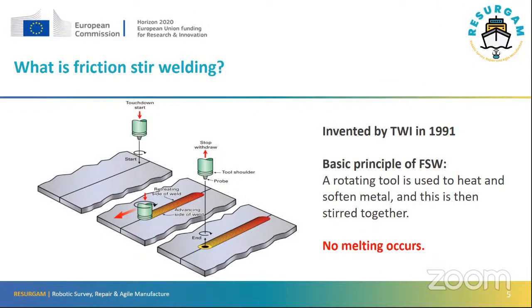Initially, friction stir welding was invented 30 years ago by the Welding Institute, and it's a very simple process which doesn't actually melt the metal. In many ways, it's very similar to milling. We have a rotating tool which we lower down onto the surface of the metal that we're about to join. The rotating tool generates heat through friction, and that softens the metal, and then it is stirred together. The important thing is that we don't actually melt the metal at all. So we get a very strong bond.